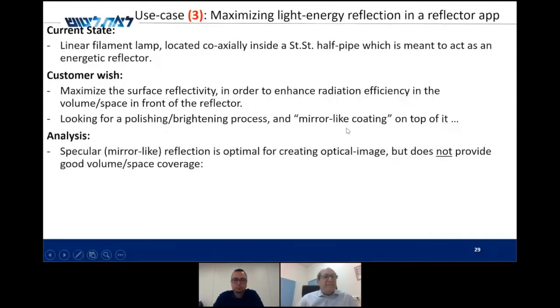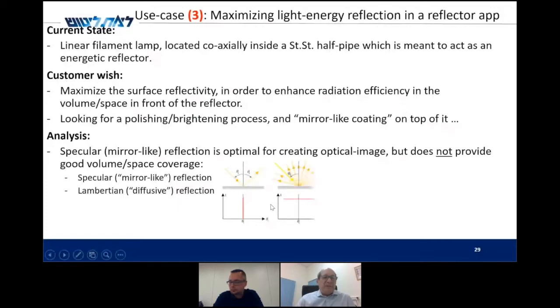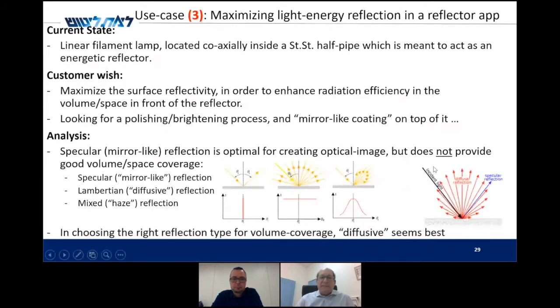And then we said, indeed, specular or mirror-like reflection is optimal for creating optical images, but not necessarily for good volume or space coverage. If you see here, specular reflection goes in one single direction. If you use Lambertian or diffusive reflection, you can cover the space or the volume in front of the reflector. And in some cases, you can get a mixed or haze reflection. So clearly for reflectors, this is the solution of choice.